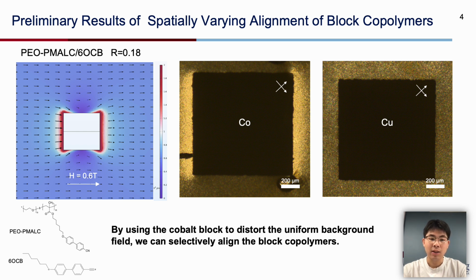By finite element analysis of the magnetic field, we can find that when we apply a uniform background field to the cobalt block, the cobalt block will distort the uniform magnetic field by strengthening the field intensity on the left and right sides, but weakening it at the top and bottom. We also got corresponding experimental results by POM.